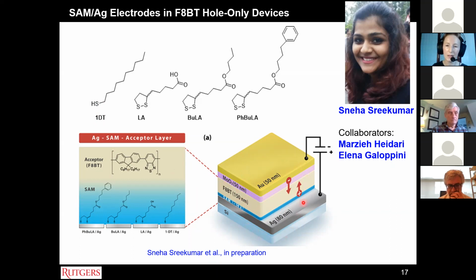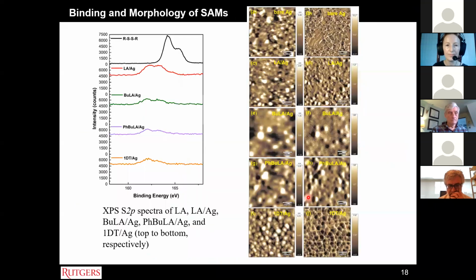And then we studied their performance in these hole-only devices, similar to what Shankar had done previously for the oxides. We confirmed the binding of the self-assembled monolayers to the silver using XPS of the sulfur 2p peak. And you can see compared to the neat compound, the self-assembled monolayers on silver show shifting to lower binding energies of the sulfur 2p peak, which indicates that it has bound to the silver.